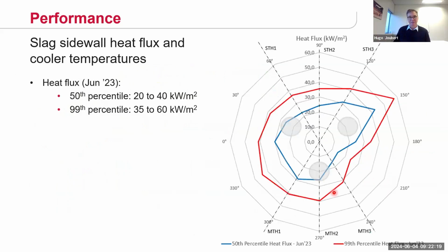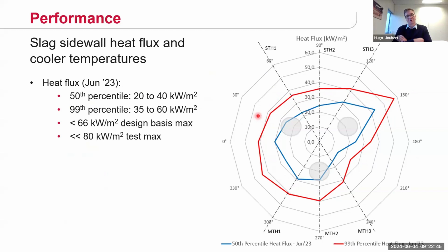during the test. This graph also shows the heat flux around the circumference of the furnace through the composite cooler sidewall. The blue line indicates the 50th percentile around the circumference between 20 and 40 kilowatts per square meter. And the red indicates the 99th percentile between 35 and 60 kilowatts per square meter. And again, that's lower than the design base maximum and quite a bit lower than what we achieved as a maximum during the test work.